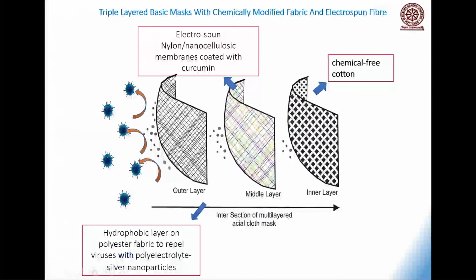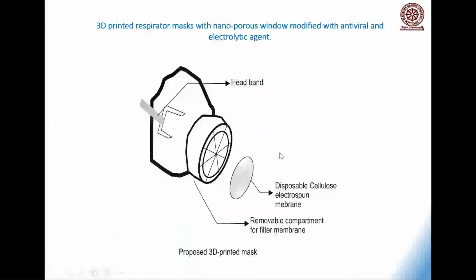Several universities were involved. You see, when coronavirus comes, the outer layer is hydrophobic. It can repel the coronavirus. And the middle layer, if at all some coronavirus is getting into the mask, has a coating of nanocellulose, which is positively charged. And you all know that virus has a protein envelope and is negatively charged. So this middle layer can deactivate the virus by electrostatic interaction. And the innermost layer is made of cotton, which is in close proximity with your mouth. And you see our mask design, the outer layer, the middle layer, inner layer. And my colleague from the US said he is going to make it by 3D printing process.